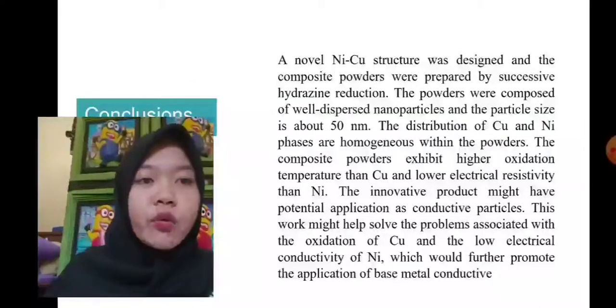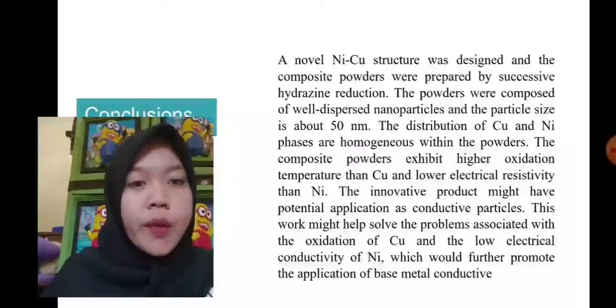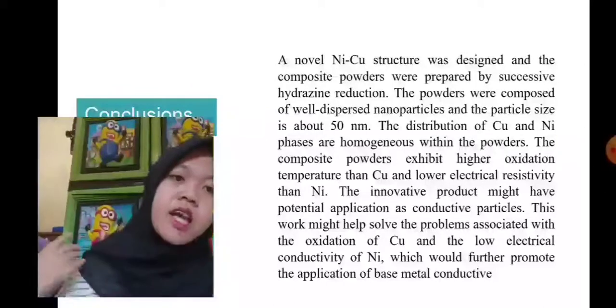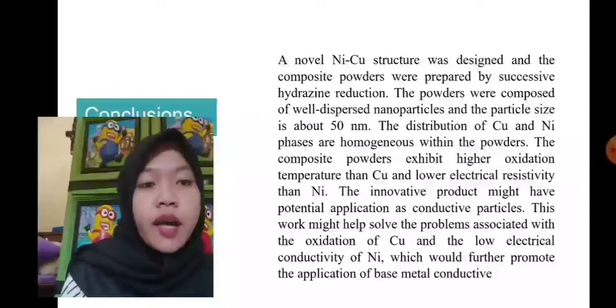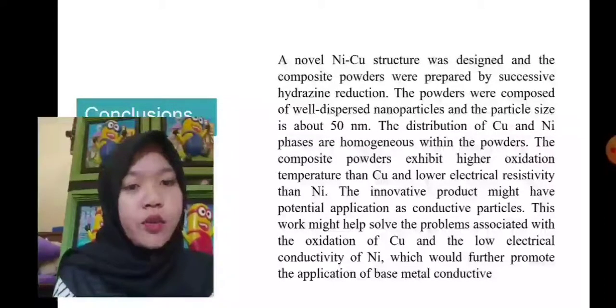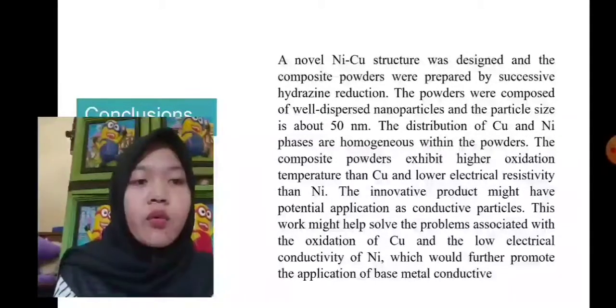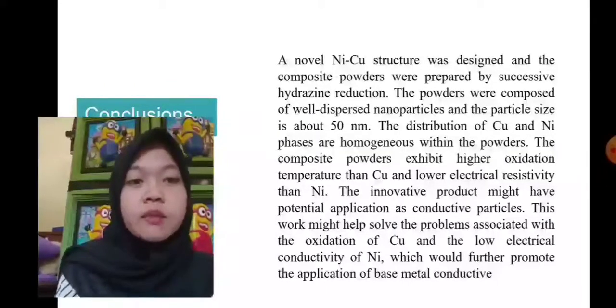The distribution of copper and nickel phases is homogeneous within the powder. The composite powder exhibits higher oxidation temperature than copper and lower electrical resistivity than nickel. The innovative product might have potential application as conductive particle. This work might help solve the problems associated with the oxidation of copper and the low electrical conductivity of nickel, which would further promote the application of base metal conductive powder.